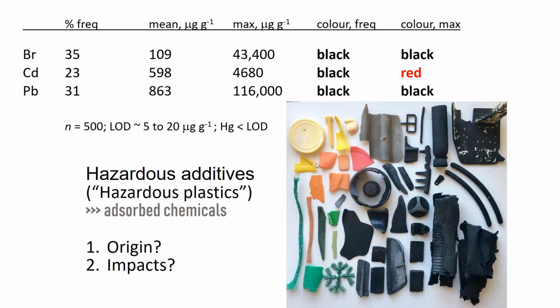Now, if we examine some of our measurements, if we take, let's say, 500 samples from a beach near here, with a limit of detection of, let's say, 10-20 microgram per gram, we find that 35% of these plastics contain bromine, 23% contain cadmium, 31% contain lead. And have a look at the LODs here. These are above sort of 5-10 microgram per gram. And when we were talking about these chemicals that were adsorbed on the surface, we were looking at values that were sort of nanogram per gram, thousands of times lower than this.